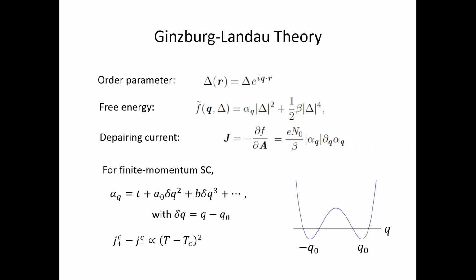Again, at the quadratic level, now the coefficient as a function of the Cooper pair momentum Q involves a much more interesting landscape. Because in the ground state, the superconducting state chooses to have a finite momentum pairing, it means that if you plot this alpha Q as a function of Cooper pair momentum Q, it has a minimum no longer at Q equals zero, but at some finite value, Q naught, minus Q naught.